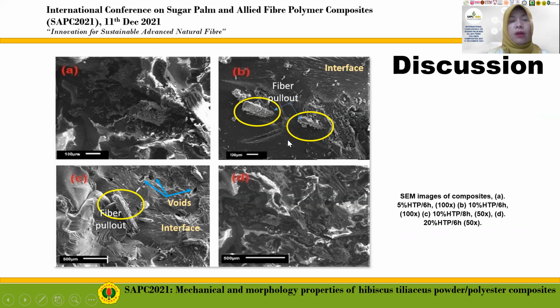Furthermore, figure B shows a tighter interfacial bond between hibiscus powder and resin in the composite than the other composites. This supports the reason why the strength of the 10% powder treated for 6 hours composite is the highest compared to other composites.